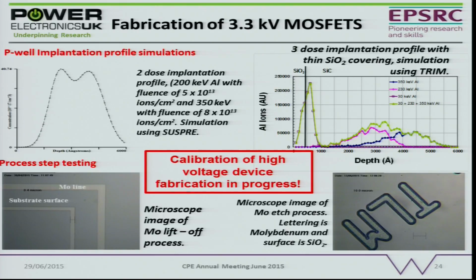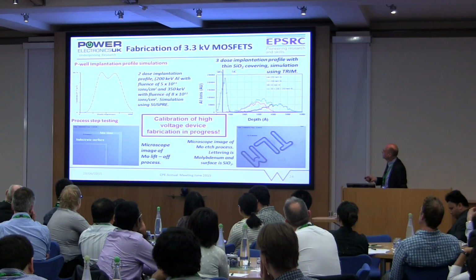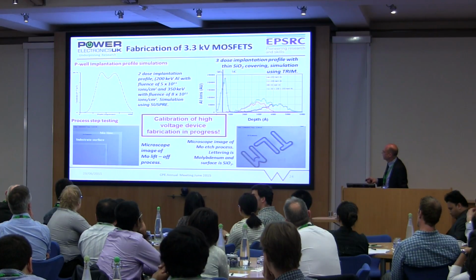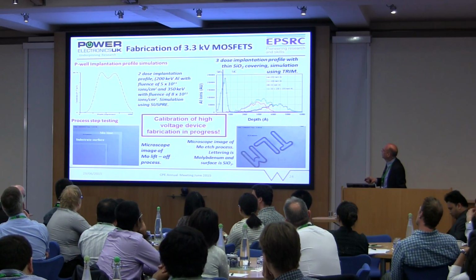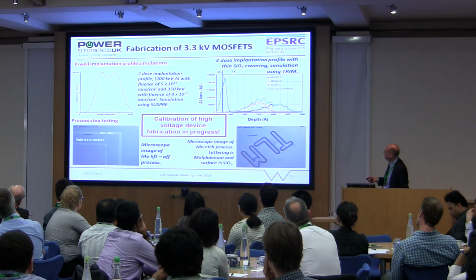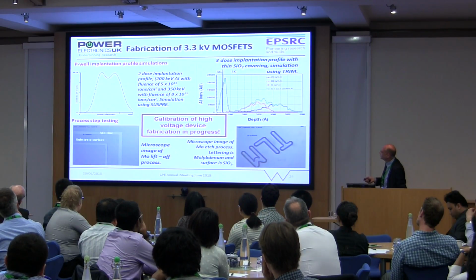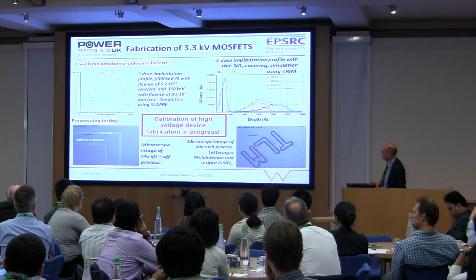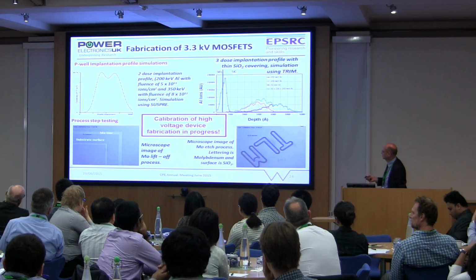We've also been doing quite a bit on characterization of implants. So these are simulated implant profiles, and we've also taken those through this simulation program and compared it with SIMS measurements on the actual devices and found them to be pretty much identical.